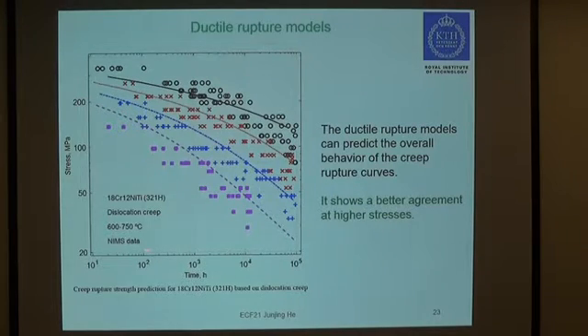Here are the results for the ductile rupture models, and the experimental data is still the same data, but the model is based on the fundamental models of dislocation creep. So here the ductile rupture models can predict the overall behavior of the creep rupture curves, and also it shows better agreement at higher stresses.